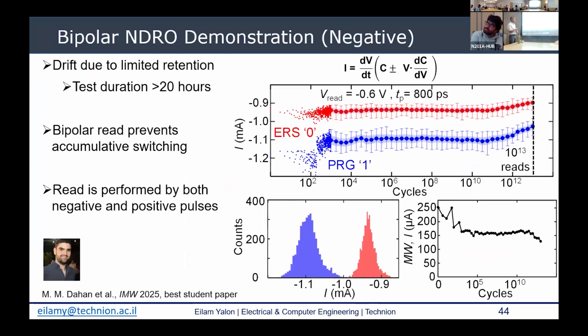So with that, we applied some short pulses to read out, and we got to 10 to the 13. This was limited by test time. The device did not disturb the state. It preserved the state up to 10 to the 13. And this is just reading out the current, which doesn't show a very good memory. It shows a memory window, but not a very good one.